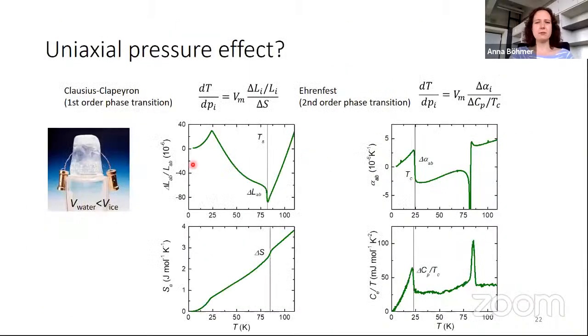And what is that? One thing we can learn is uniaxial pressure effects. This is basic thermodynamics. You might have seen it before. The relations are quite famous. One is Clausius-Clapeyron. It says that the pressure derivative of a certain temperature is given by the length change of a sample at that temperature, or the volume change divided by the entropy change. You can see that with ice. It's quite intuitive. Ice has a larger volume than water, so if you compress ice, you'll melt it. It wants to be water. It does not want to be ice anymore. That's what this relation means.